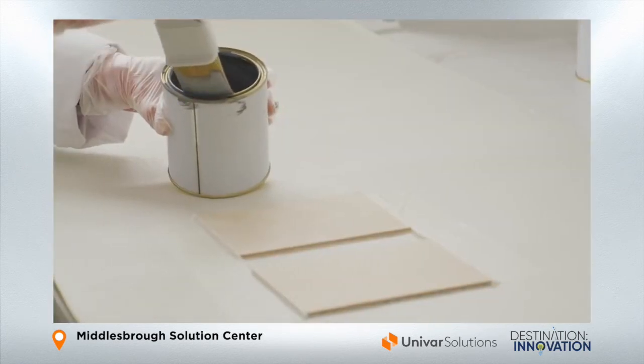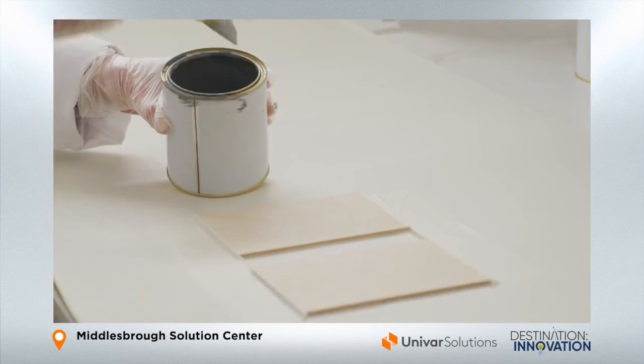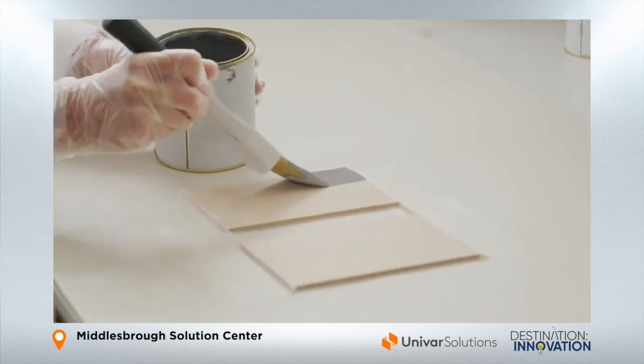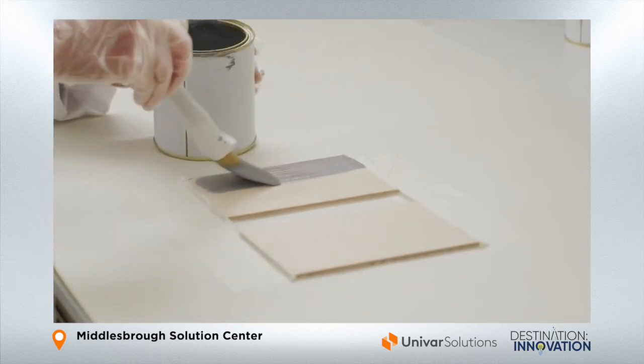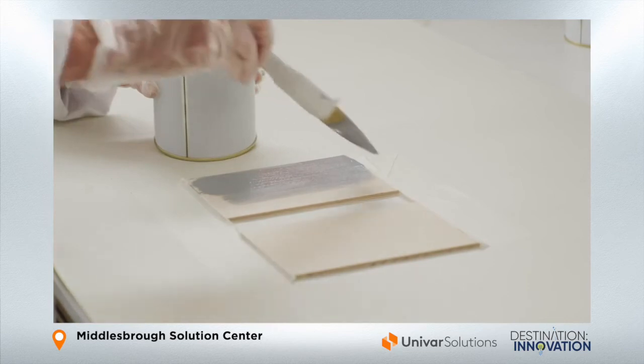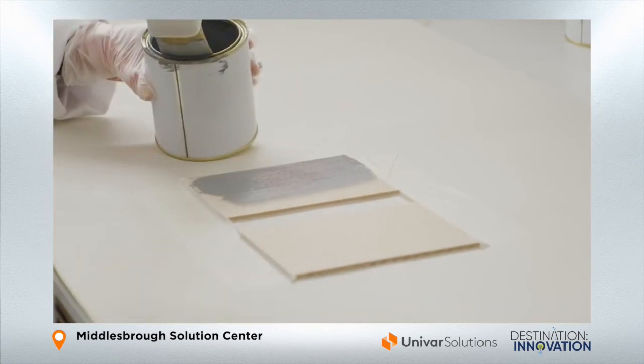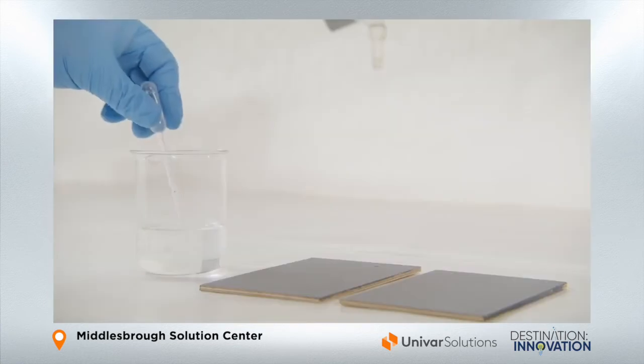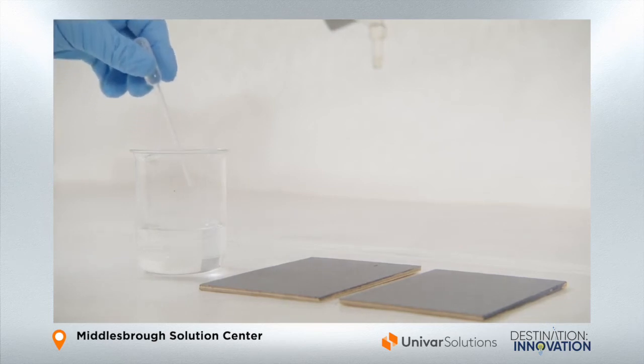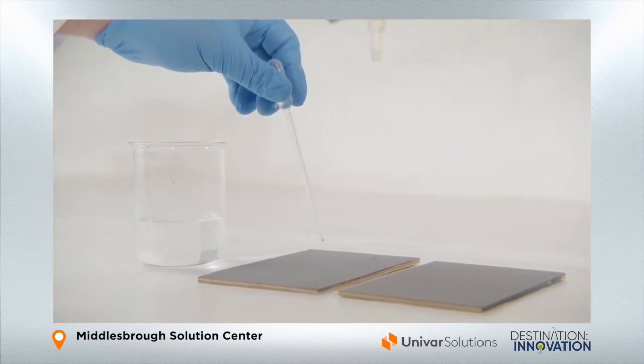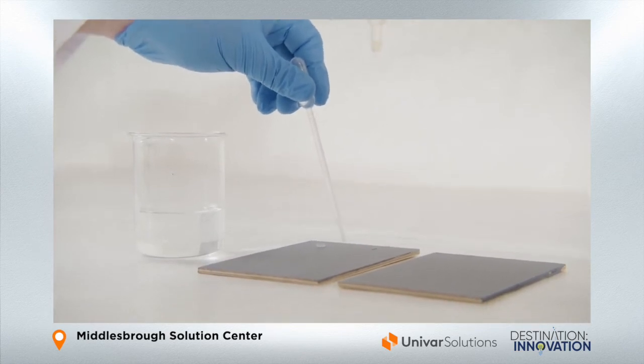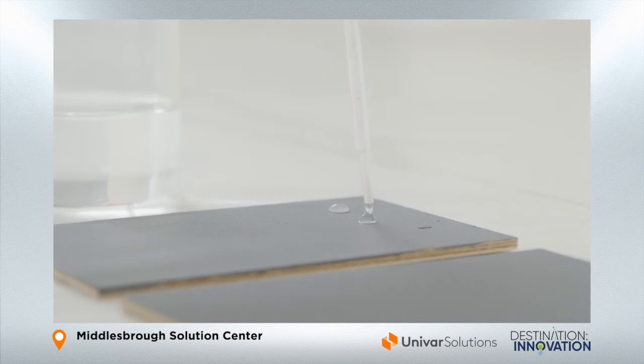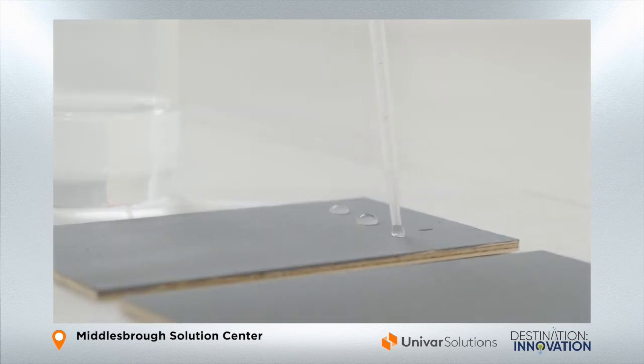So that's something we did in the lab as well, actually. Just painted wood panels with a pigmented waterborne wood coating. The one on the left contains just a small quantity of a silicone additive, whereas the one on the right doesn't contain that additive. So just applied the paint onto the panels and left it to dry so it was touch dry, and then just simply put some water on the surface. And what you can see almost immediately on the panel that contains the silicone additive, you do see quite a nice water beading effect, because this additive, with it being silicone based, has good water repellency as well.